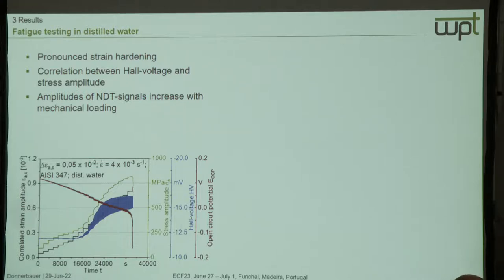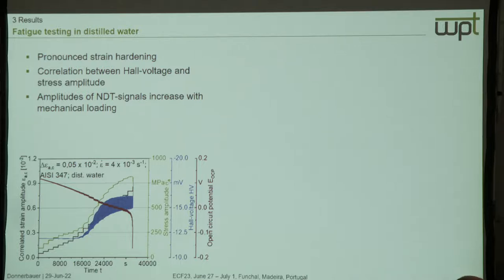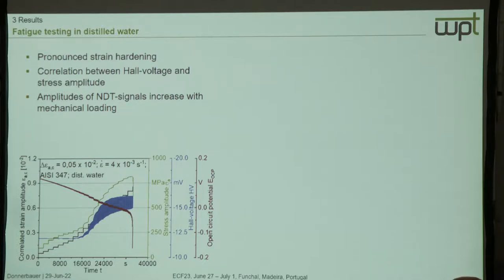The stress amplitude starts to increase sharply above strains of about 0.3 percent. The Hall voltage also starts to increase at the same time as the stress amplitude increase — we can expect that the magnetic measurement gives a better signal when we have more ferromagnetic phase content. The signal from the Hall voltage appears noisier as the test goes on, but this is because when the specimen moves into tension the Hall voltage goes up, and back into compression it goes down, showing the same triangular form as the constant strain rate loading.